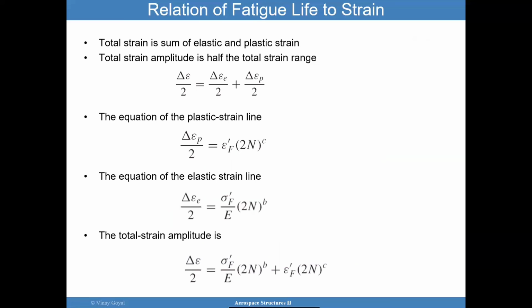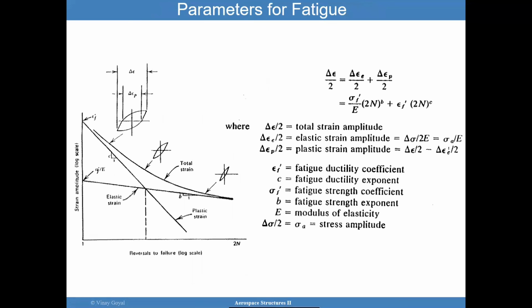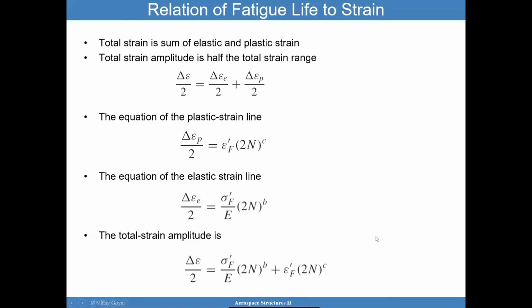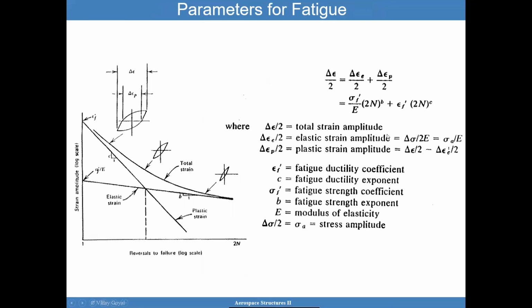So the total strain amplitude, if you're to do it in terms of total strain amplitude, the number of cycles to failures can be calculated using this formula. And here the total strain amplitude considers both the plastic and elastic. And b becomes the fatigue exponents, which are provided to you. Parameters for fatigue, this is another way to look at this same formula here, but shown to you in terms of the stress strain curve. So you can look at it all in one place.